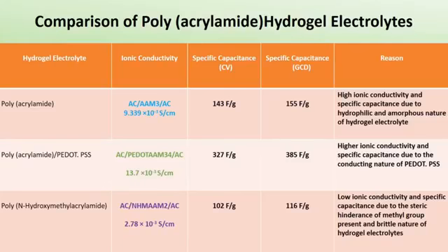And results show that polyacrylamide hydrogel added with the PEDOT and PSS shows higher ionic conductivity and specific capacitance due to the conducting nature of the PEDOT and PSS. So they are very good conducting polymers.